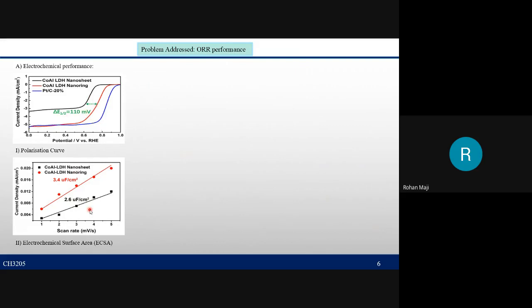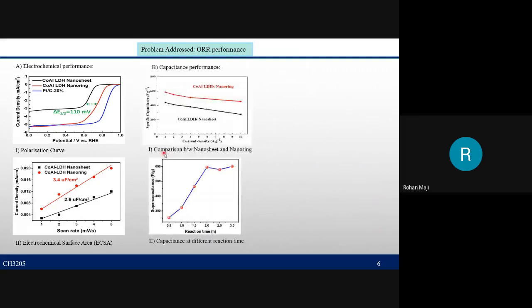Now, this figure below reveals the enlarged electrochemical surface area of the nanoring, which suggests that more edge sites could be exposed as active sites in the nanoring compared to the nanosheet. In the capacitance performance, we can see nearly 50% increased capacitance for the nanoring, which indicates that more active metal sites participated in the reaction and reaches the peak after 2 hours of the reaction.